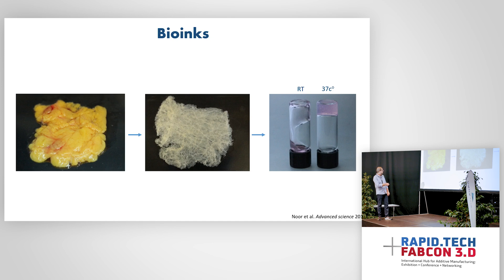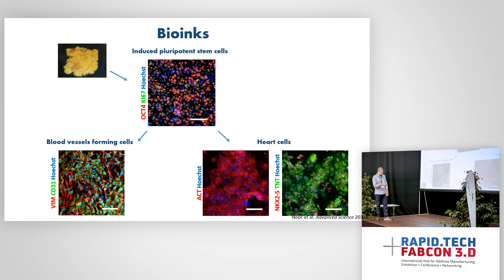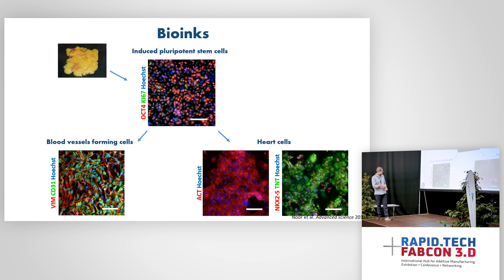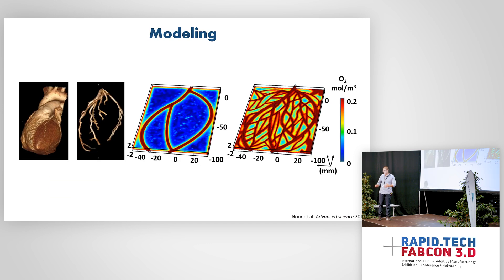This is how it looks. This is the fatty tissue; this is after we take all the cells out, and after additional processing, we are left with a thermoresponsive hydrogel made mainly of collagen, which is liquid at room temperature and solidifies at 37 degrees. This is our bioink — this is what we are printing. Meanwhile, we take the fat cells and genetically reprogram them to become stem cells. Then we proliferate and duplicate them to have enough quantity, and we differentiate them into blood vessel forming cells and heart cells for the printing.